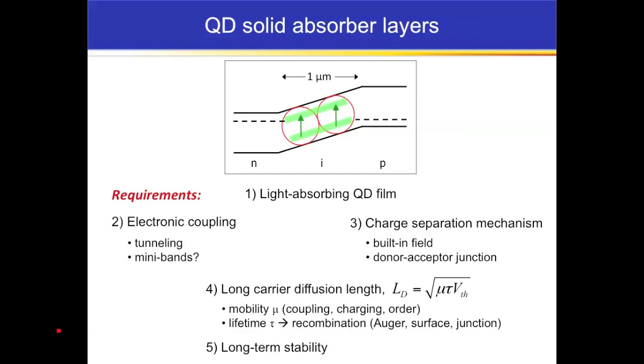What do you actually need for a quantum dot solid in terms of a photovoltaic absorber layer? Well, you need all the normal things. You need to have good light absorption. You need to have a conductive thin film, so the quantum dots have to be talking to one another. You have to be able to charge separate, so you need to have some sort of built-in field, perhaps, like in a PIN structure. You need to be able to then collect those carriers in high yield, and so you need a diffusion length that's long. And in the case of quantum dot solids, we're talking about boosting the mobility and boosting the lifetime.